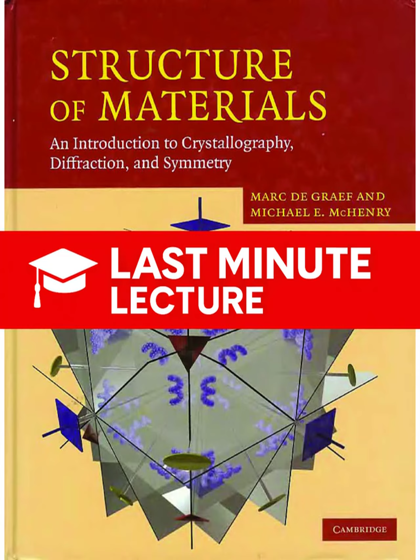So let's take kyanite. Kyanite is the high-pressure, low-temperature polymorph. Structurally, its aluminum ions are exclusively octahedrally coordinated. They're all AlO6. And what does that structure look like? It's tough. It's built from these chains of edge-linked octahedra running parallel to the c-axis, and these robust chains are cross-linked by the isolated SiO4 tetrahedra. So kyanite is all about those tightly packed, high-pressure octahedra. What changes when we look at sillimanite?